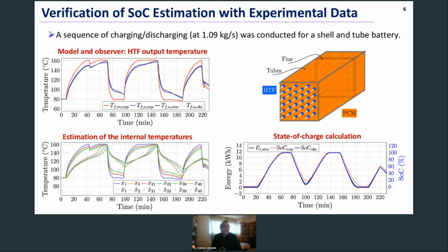Simulation results were compared against experimental data, which has been available and taken from published references. This data basically consists of the input and output temperatures of the heat transfer fluid and the state of charge. The simulation considers a sequence of charging and discharging processes. The heat transfer fluid in this case has a constant value of mass flow rate of 1.09 kilograms per second, just to simplify things. When looking at the results, the top graph shows the input temperature of the heat transfer fluid with a red trace. The output temperature in turn is given with a blue trace.